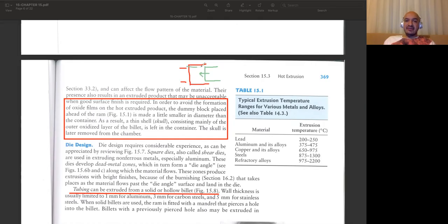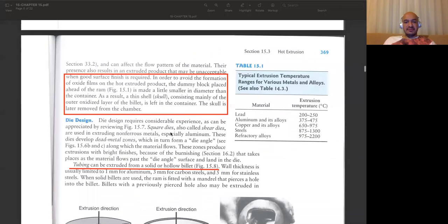These sides actually will not be extruded, okay? And this is the thing we want to have, since these are oxide films. So once you use a smaller ram, these will not be extruded, and we will have high quality workpiece at the end of extrusion. And these oxide films will be remaining inside the chamber. And once the process is over, you can remove your ram and clean the chamber. This way, the quality of your workpieces will be improved.